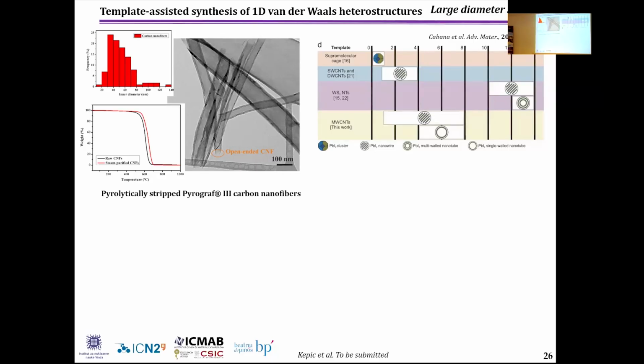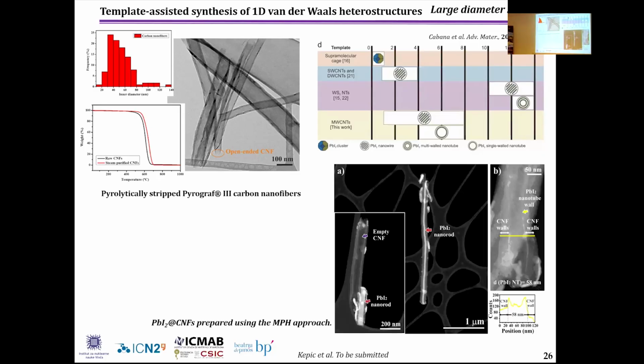Because before, wider structures, like for example, tungsten sulfide were used, but in this case, rod or multi-layer inorganic systems were formed. So we use pyrolytically stripped pyrograph carbon nanofibers to prepare this hollow system. So using the molten phase approach, in this case, of course, carbon nanofibers were able to encapsulate both rods, but also nanotubes, which reach up to 60 nanometers diameter. So this is the first time that single layer nanotubes are encapsulated in a big platform.